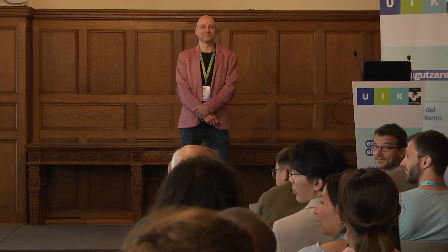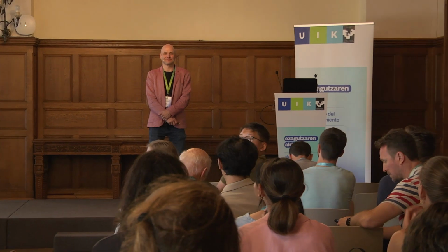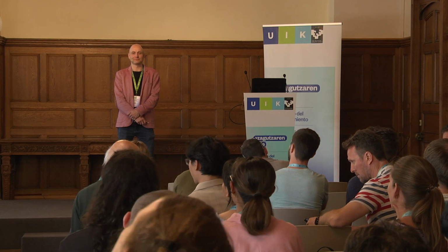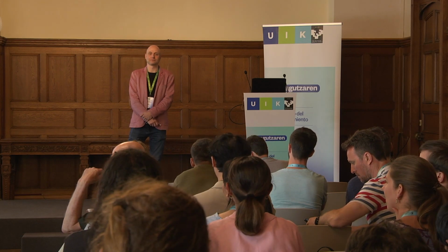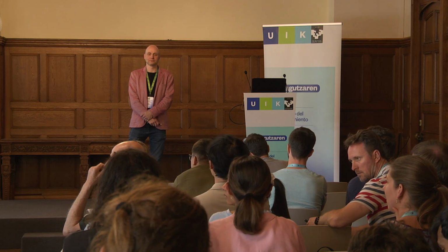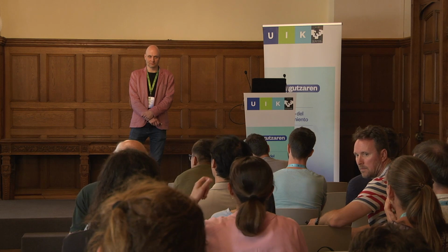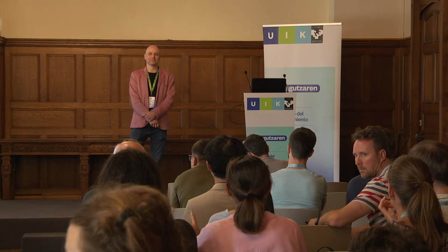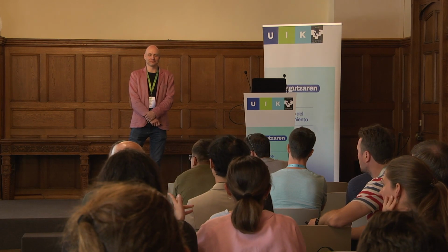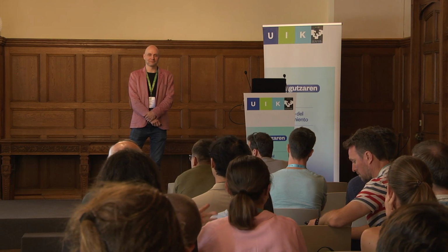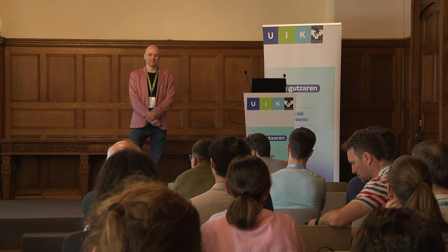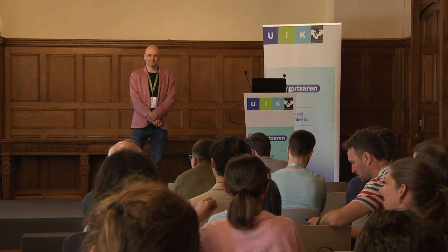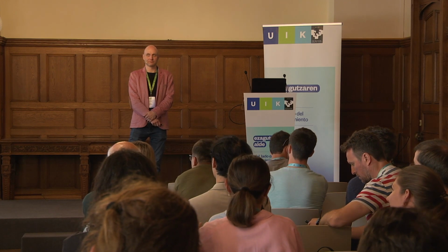We have a question here. Okay, thank you for the talk. It was very wonderful, and I like to see a lot of models because I also work with them. My question comes in a practical way. So, for example, let's take a model, doesn't matter which. You calculate the near-field interaction between the tip and the sample at certain tip heights, from 1 nanometer to 50 nanometers. You have to select a good enough number of points, then interpolate, with a linear, polynomial, or spline interpolation. Then you have to demodulate that, and choose different packages for the demodulation. So you have a lot of uncertainties there, and different ways to process or demodulate the data.